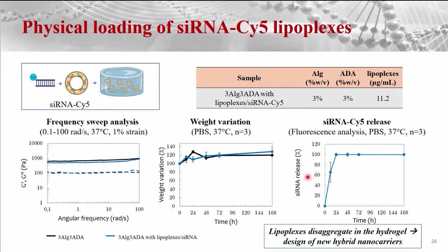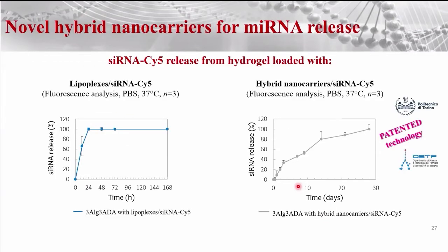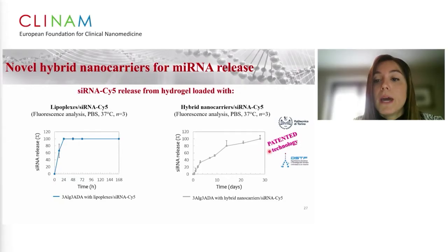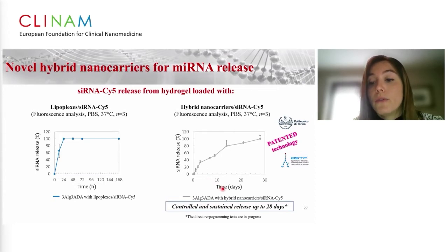This result suggests that lipoplexes can disaggregate in the hydrogel due to a possible electrostatic interaction with the compounds of the hydrogel. So based on this result, we designed new hybrid nanocarriers. In collaboration with the University of Turin, with Professor Arpicco and Stella, we patented a new technology based on coating of lipoplexes that improves the release of microRNA up to 28 days.